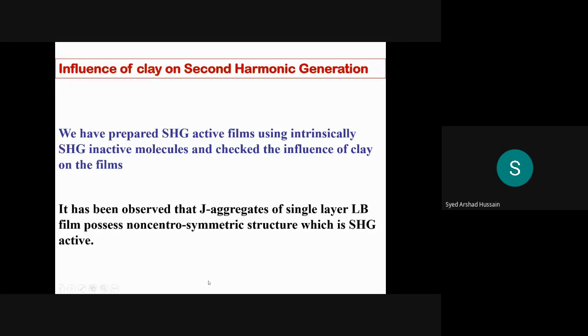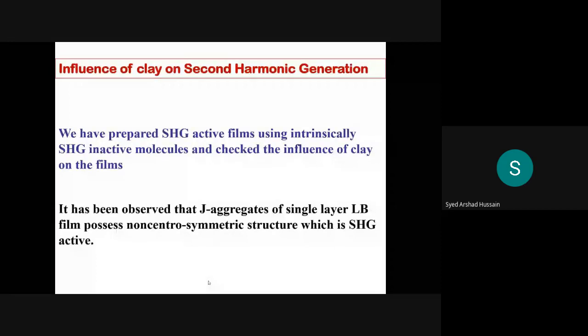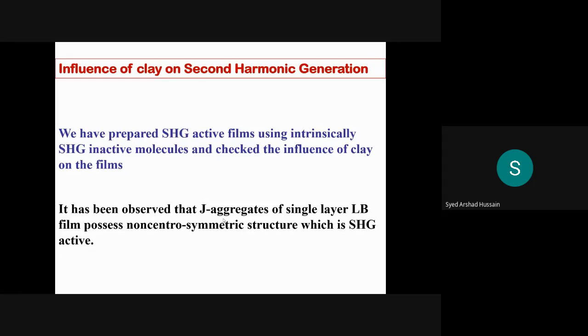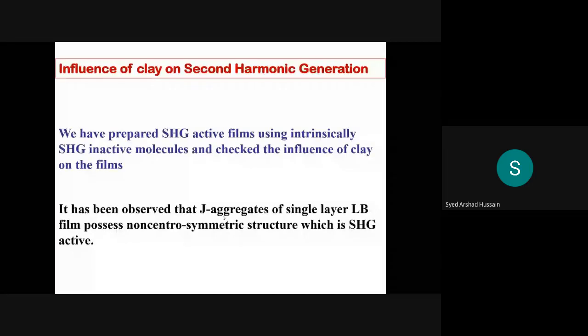So in our case, what we did, we prepared some J aggregates of organic material using LB systems, and then we demonstrated that it's possible to have this second harmonic generation using this kind of system. One of the prerequisites for second harmonic generation is that the system should be non-centrosymmetric. If your molecule is intrinsically non-centrosymmetric, you will have this SHG. But using the LB system, if you prepare J aggregates, then even a symmetric molecule can show, as a whole, a non-centrosymmetric structure, and one can have SHG activity.